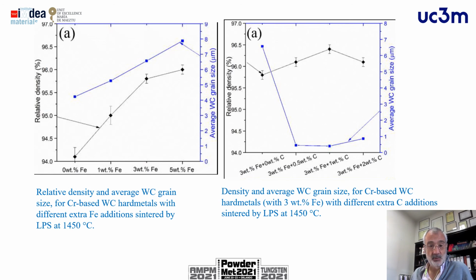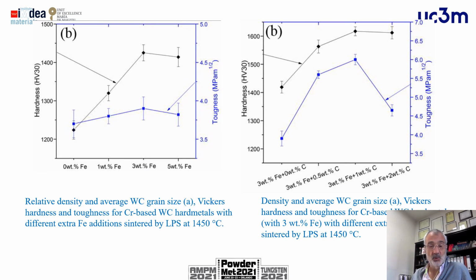And as you can see here, using in the order of 3% of iron and 0.5% of carbon, we can reach the lowest average tungsten carbide grain size in the final bulk material with good levels of relative density. Later we will analyze the microstructure a little bit better, but also the hardness that we can reach adding these amounts of iron in combination with some amounts of carbon. You can see here that this combination of 3% of iron and 0.5% of carbon can reach good levels of toughness, but not so high if we compare later with other materials obtained by spark plasma sintering, but the highest levels are in these amounts of carbon, reaching also good levels of hardness.